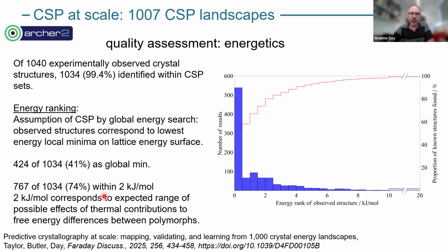To give you an idea of why 2 kilojoules per mole is important, if we do a larger scale study of energy differences between polymorphs, which I mentioned earlier in the talk, and look at lattice vibrational energy differences between polymorphs and the contributions you get from those vibrations of your molecules, that distribution typically goes up to about 2 kilojoules per mole at room temperature. So that tells us that within the errors we have from leaving out those vibrational contributions to the free energies, all of these are essentially predicted as good as we can expect.